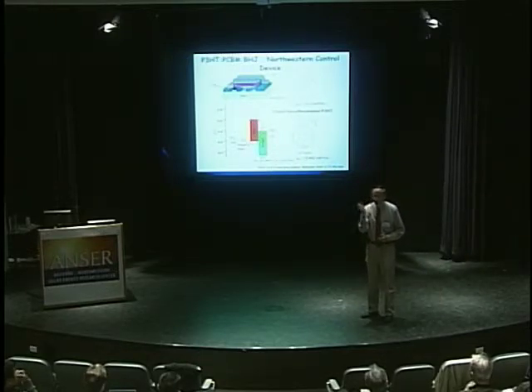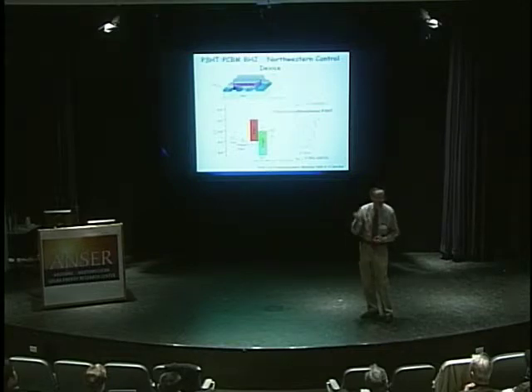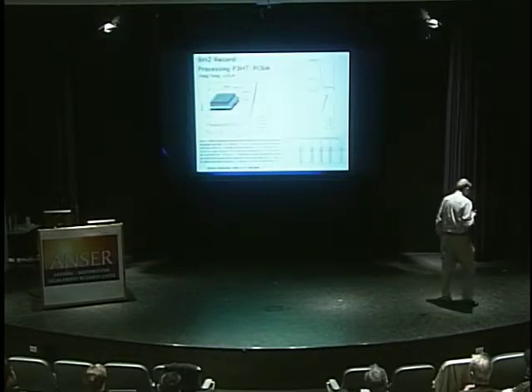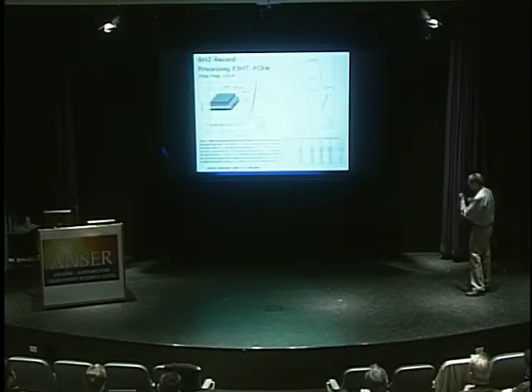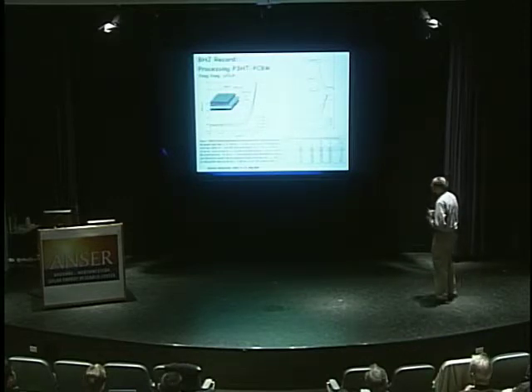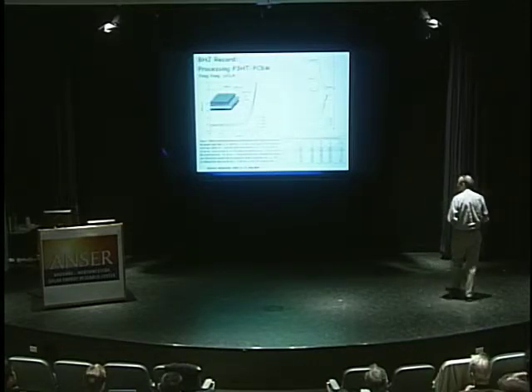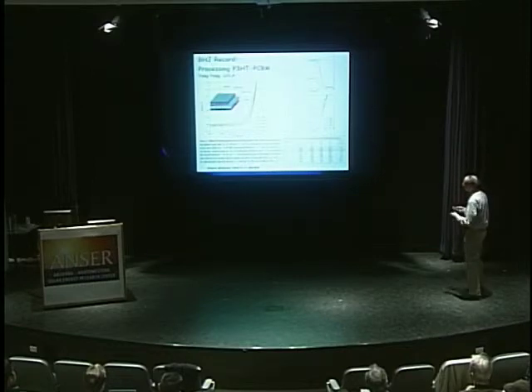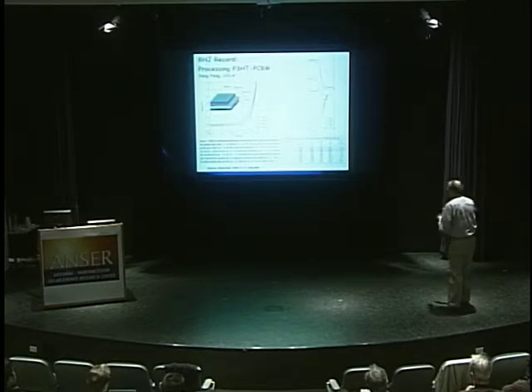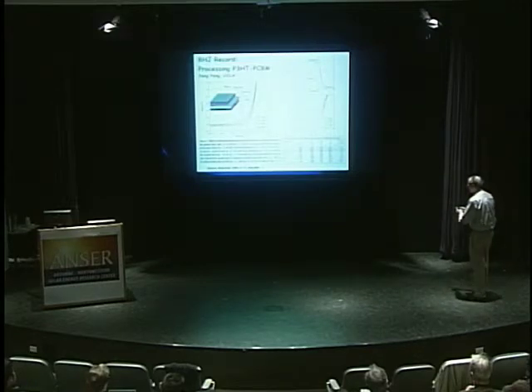For a layer that will extract holes and block electrons. And the benchmark, sort of our competition, or what we've got to better, this is some very beautiful work by Yang at UCLA, and we heard it mentioned already. Basically, all he did is take this material and try different annealing protocols. And when he hits it just right, you can see here a nice, relatively square curve.